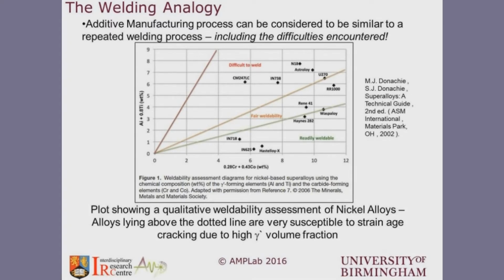But as we move in that high temperature capability of nickel superalloys toward materials like CM247, we start to appear in the difficult to weld envelope. So what is the real difficulty in welding or additive manufacturing of nickel superalloys? What's the difficulty in making multiple welds of that material, which is the same thing we see in additive manufacturing?